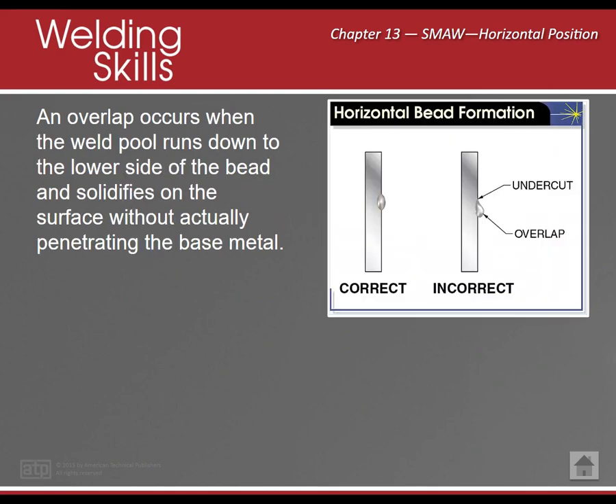An overlap, or also known as a cold lap, occurs when the weld pool runs down to the lower side of the bead and solidifies on the surface without actually penetrating the base material. So if you have a 5/16 wide weld and you have overlap that occurs in the bottom half of that weld, you're only getting maybe 3/32 to an eighth of an inch worth of actual weld that is penetrating into the base material. So it's just like having a weld that's half the size of what the weld is supposed to be.